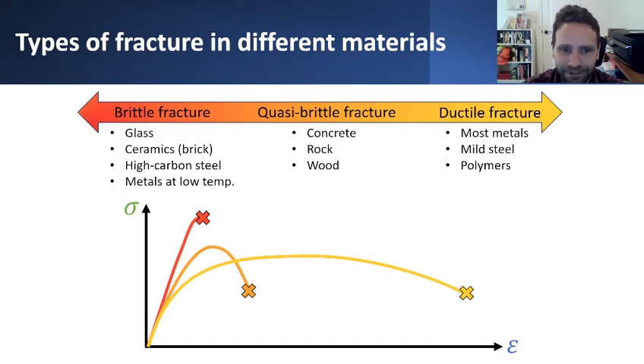It just fractures. So there's no energetic dissipation through other modes of dissipation like plasticity or other types of permanent deformation behaviors. It just happens suddenly and instantaneously. Now, at the intermediate range of these behaviors, you might have quasi-brittle fracture, which is still quite brittle in nature, and maybe these curves as I'm showing below are a little bit of an exaggeration. But really, quasi-brittle fracture accounts for the fact that fracture doesn't necessarily happen instantaneously in a lot of materials.